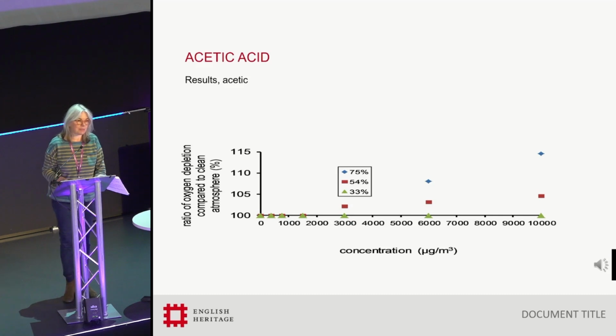High levels of acetic acid, which can be found in timber composites, paints, and adhesives, are known to cause corrosion above 54% relative humidity. The vertical axis shows oxygen consumption. The horizontal shows concentration of acetic acid.